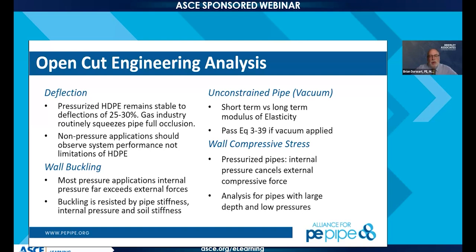The thing that the trench fill brings to the table, though, is it's usually a granular material, which means that the deflection of your pipe, the ovalization, is going to occur usually just during construction. And once the soil is settled on the pipe and ovalized a slight amount, the sidewalls of the pipe are now being supported by the soil. That action is not going to continue to progress. You have a single short term, the pipe may be slightly ovalized, and you can pretty much calculate that if you want based on the Iowa formula and what you have for compaction in the trench, and looking at the surrounding soil to see whether that trench fill is going to remain stable.